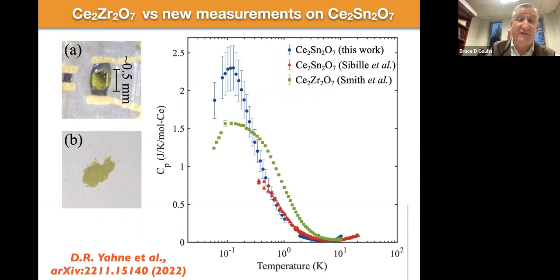Okay, and actually we can get small single crystals of cerium tin oxide and powders, and they look very nice. Actually, they don't look like they've been oxidized. They're very green and transparent, and so forth. And we've managed to do essentially a complementary set of measurements, very similar to what we did on cerium zirconate, although not as much neutron scattering. But actually, this is the low temperature heat capacity of cerium stannate from our new hydrothermally grown crystals.